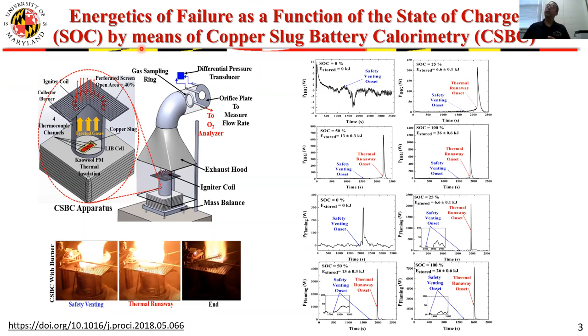So you take a given cell of interest, you charge it to a given state of charge, and you place it into a copper slug, as this calorimeter indicates, that is machined to perfectly fit the cell with the exception of one surface that contains the safety vent ports. That surface remains open. You embed thermocouples into the slug and add an electrical heater that is connected to a control power supply, and you put the whole system into an insulator to minimize heat losses.